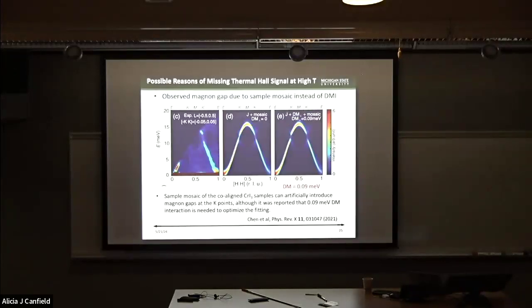Yeah. Because again, if your sample has mosaic, imagine that initially you will say, well, I'm measuring along the K point, but in reality, you are not really measuring at the K point. You are measuring a momentum point slightly away from the K point, and as a result, the intensity could be different.